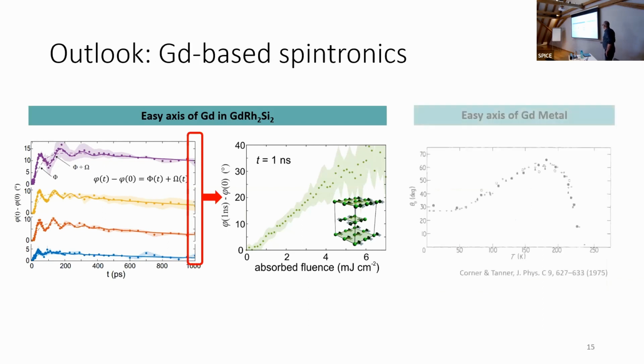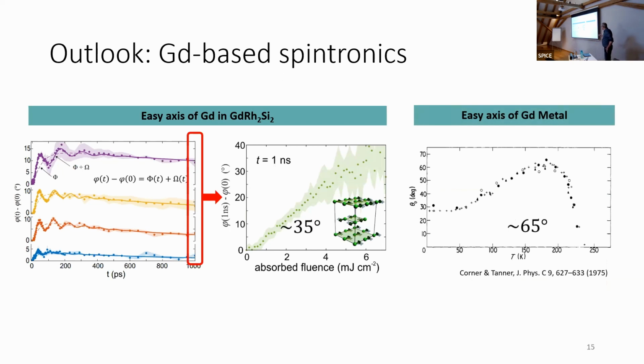Now, this is actually a pretty large effect. It's 35 degrees. But if you actually look back in literature, this is 1975, it's pretty old. This is gadolinium metal. This is the anisotropy of gadolinium metal. And it turns out that that rotates even a lot more. And this is facilitated by the fact that gadolinium is a half-filled 4f shell, and so it has very weak anisotropy, which is typically imprinted by the conduction electrons, because 4f electrons are not conduction electrons. So one can imagine an even stronger effect if you want to utilize gadolinium. And actually, even though there's a lot of ultrafast work on gadolinium metal, I've never seen anything associated with its anisotropy. Maybe somebody will do something with that.